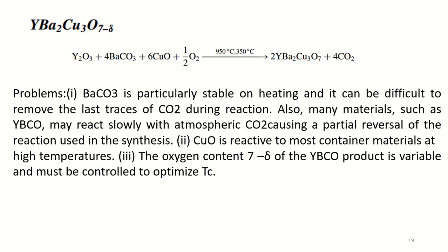The problem is that barium carbonate is particularly stable on heating, and it can be difficult to remove the last traces of carbon dioxide during the reaction. There are also many materials such as YBCO which may react slowly with atmospheric carbon dioxide, causing a partial reversal of the reaction used in the synthesis.